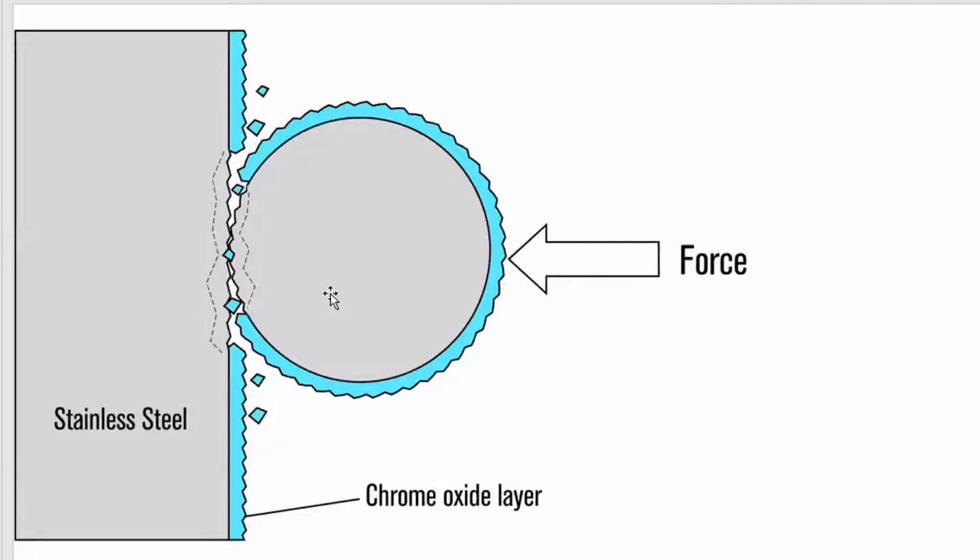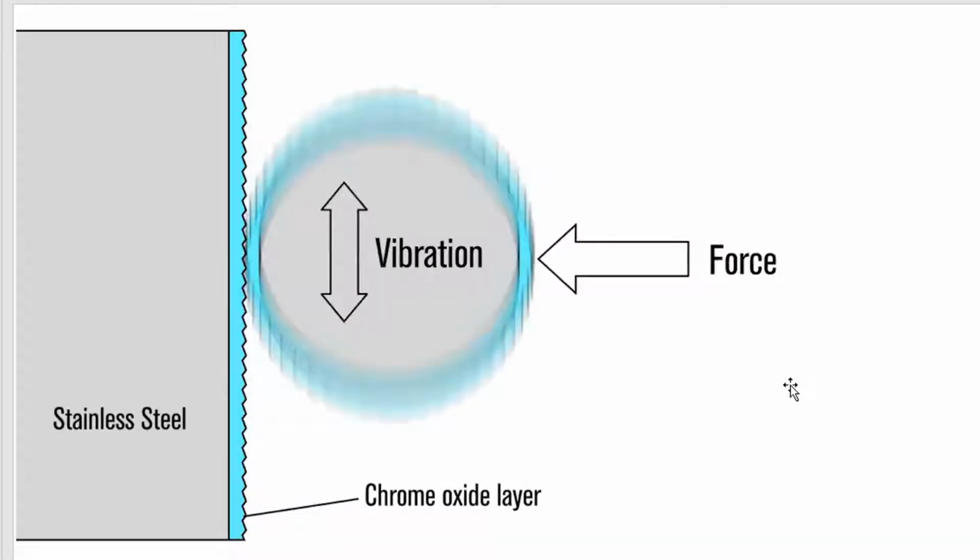You can flex those back and forth without wearing them down. And then every time this surface lifts off, it allows some air, or I really should say elemental oxygen, to find this and start corroding this. Okay, so what you're seeing is the flexure of this O-ring, but you don't have any sliding.